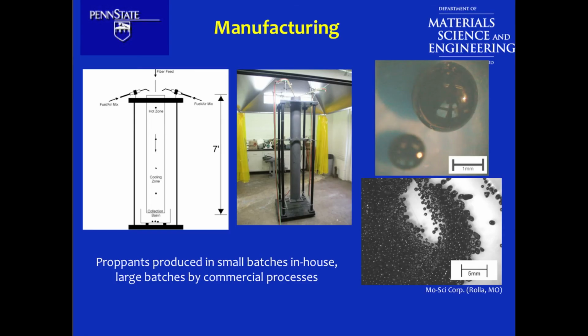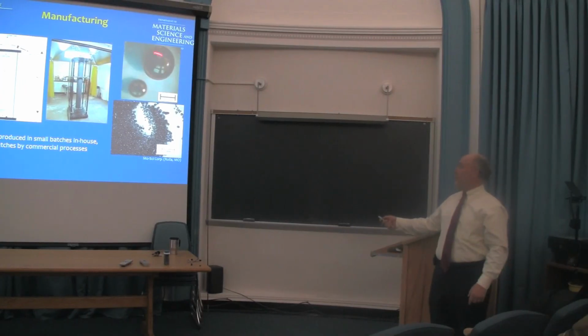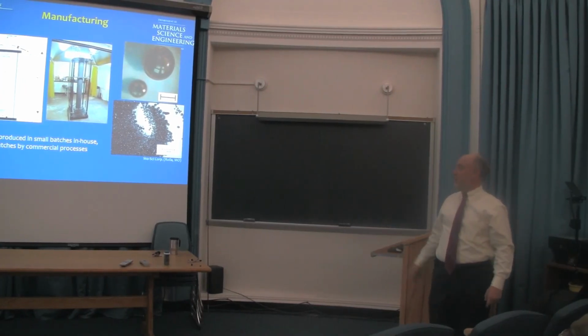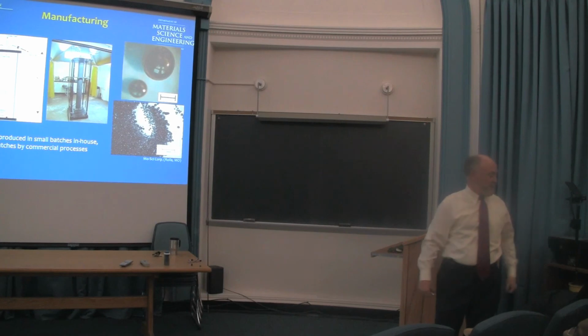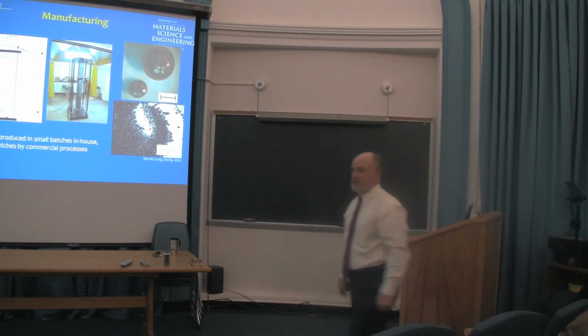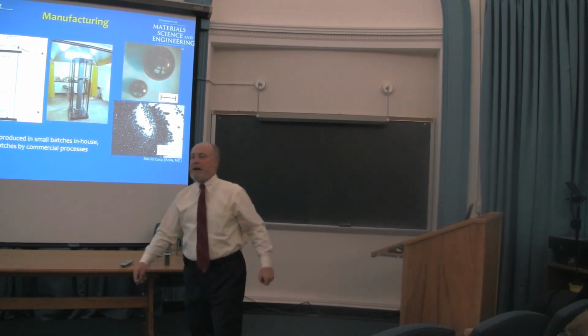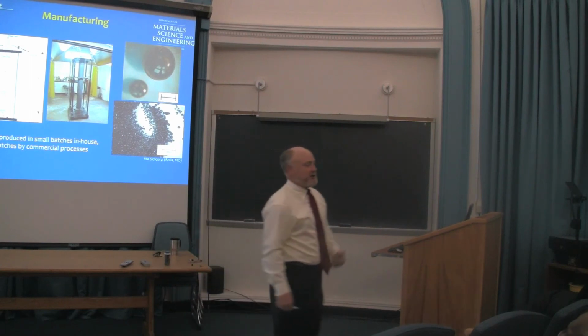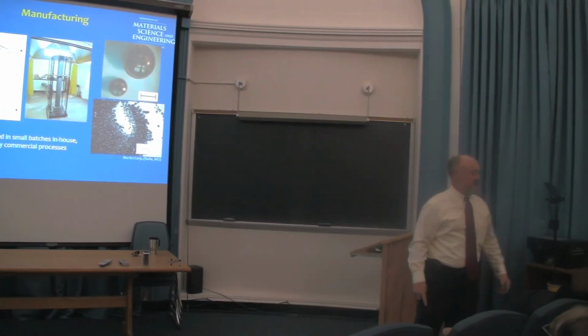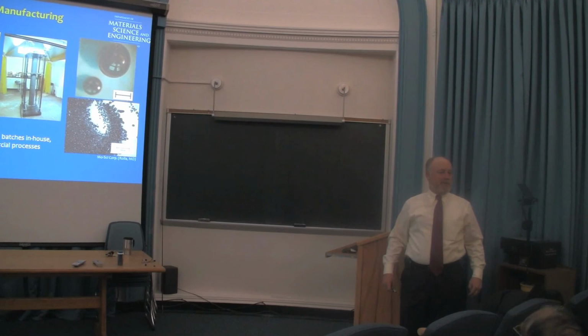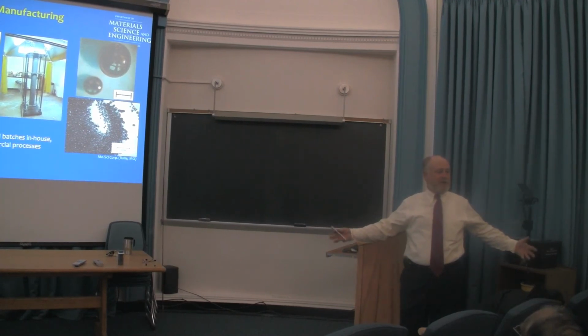First, we built the flame spheroidization tower. So this is about a 7-foot long silicon carbide tube with oxyacetylene torches. We feed the glass through in fiber form. We make the glass to begin with. And then we spheroidize it to form little balls. Here's some of the product. Falls out the bottom into a nice Tupperware container. And then you have a graduate student separate them out bead by bead for testing. So you're manufacturing about 30 cc's of material to do a whole PhD project.